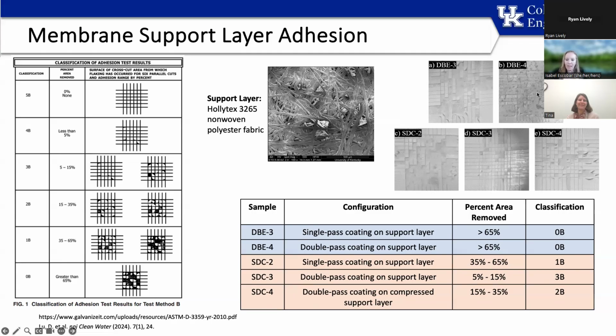There was very little actual sticking to the porous support, even though we did the pre-treatment, as you can see in both of these. With the slot die coater, we had some cases that had poor sticking, but when we sprayed the dope solution as a pre-treatment on the porous support, we were able to get good adhesion. To be in this 3B category here is not ideal yet, and maybe we need to increase the spraying time, but we were able to develop something that stayed attached.